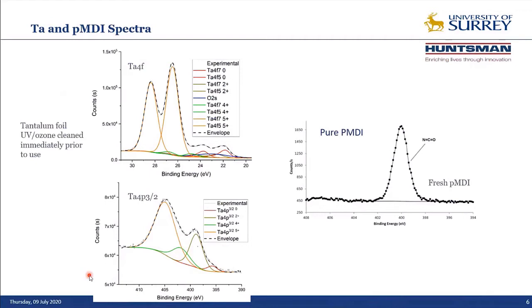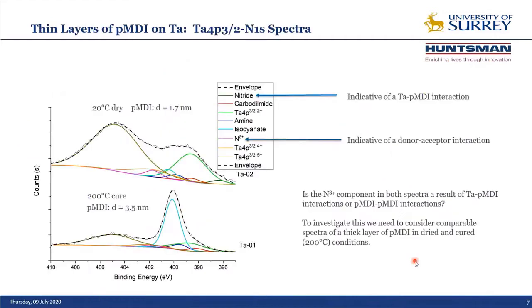If we take fresh polymeric MDI, smear it onto a piece of tantalum, we don't dry it, we don't cure it, we put it straight into the XPS spectrometer, we get a peak that we can see on the right-hand side there. It's a very symmetrical peak representing the nitrogen in the urethane group that we have in PMDI.